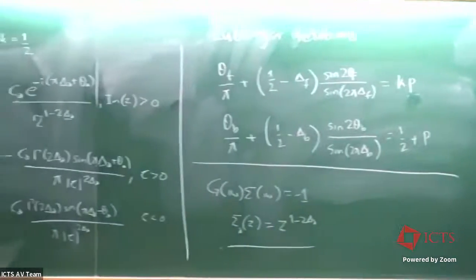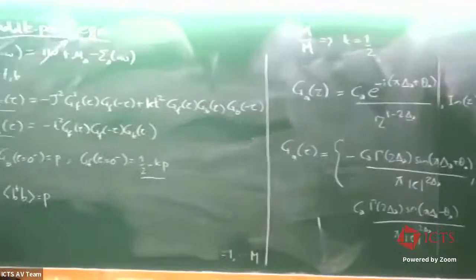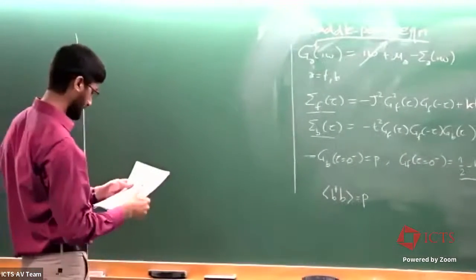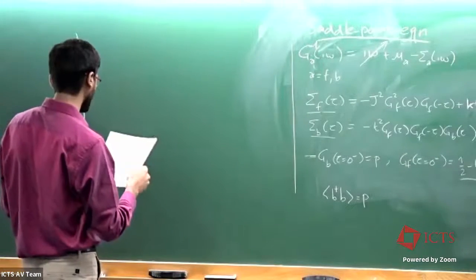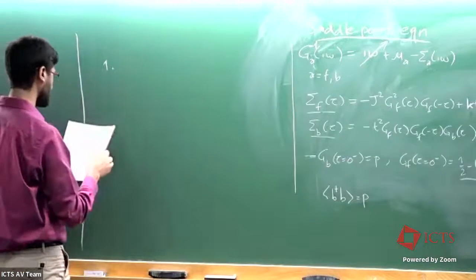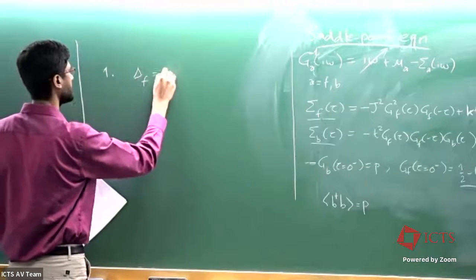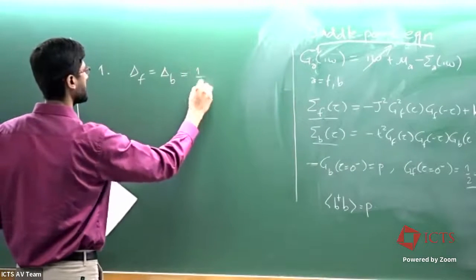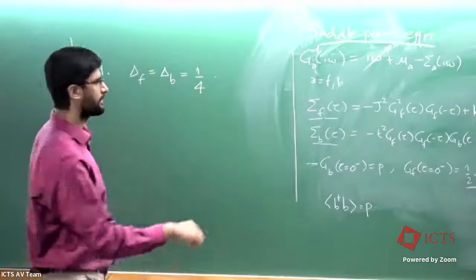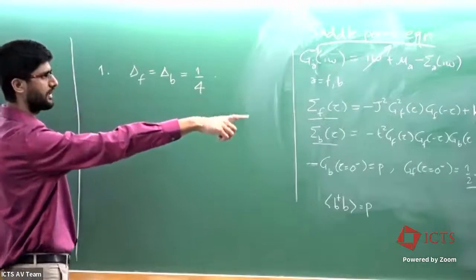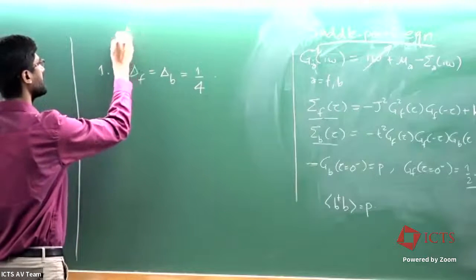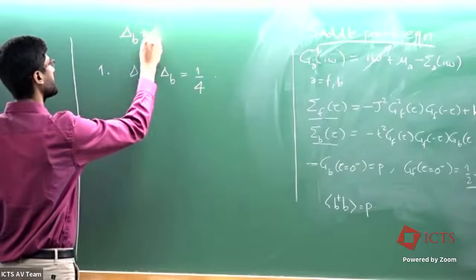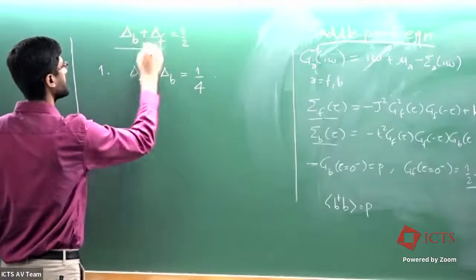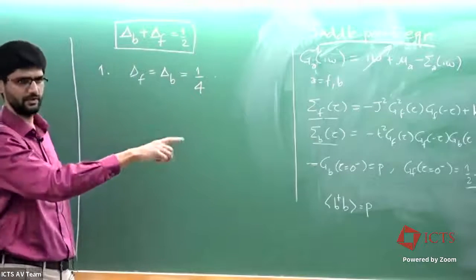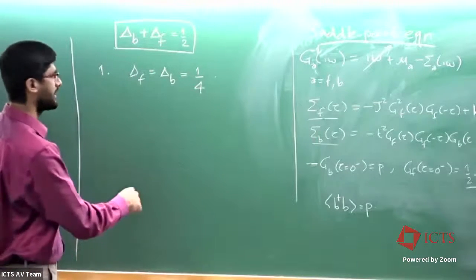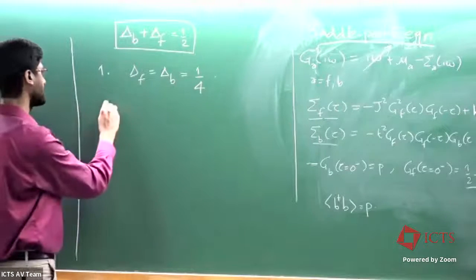And if you now do this comparison, this is how you get the set of solutions. I think, can people see this side of the board? Okay. So if you do this comparison, then you get 3 types of solution. Before that, actually, as soon as you write this relation, you immediately also get a constraint that delta F plus delta B is 1/2. And this is most easily seen if you compare the exponents in the bosonic self-energy. And now you compare the fermionic self-energy, you get 3 types of solution.